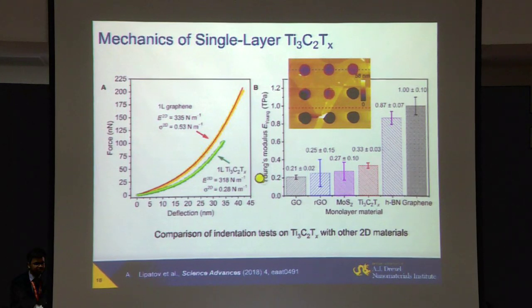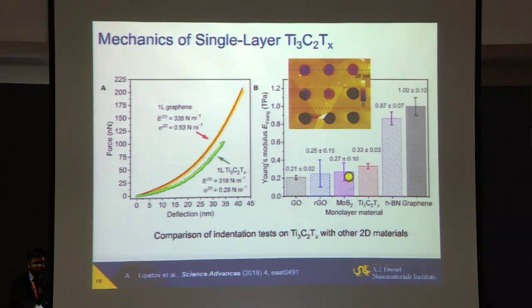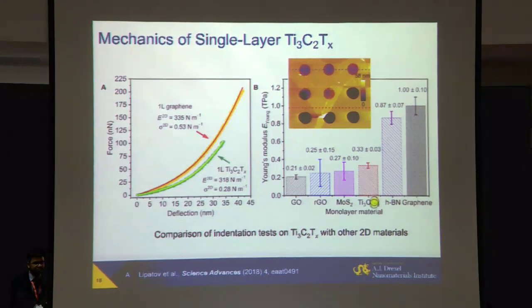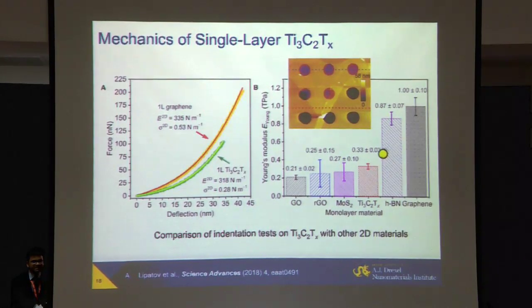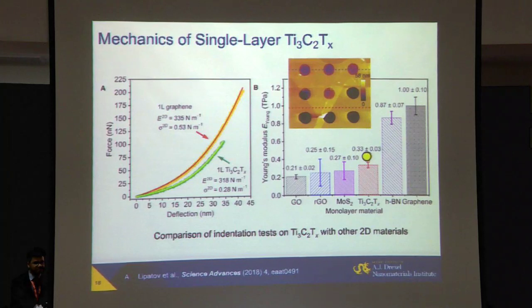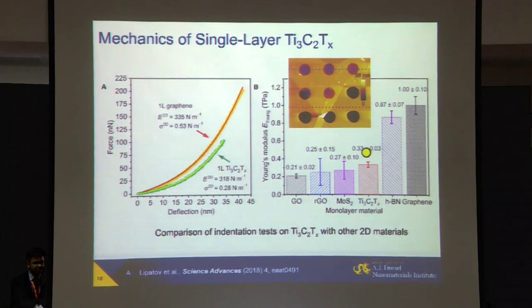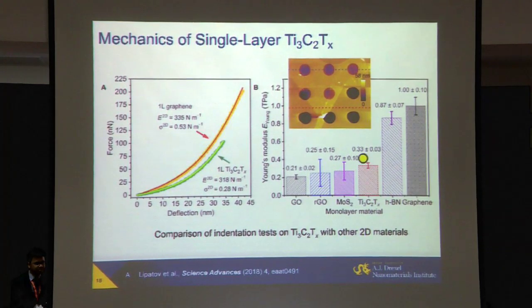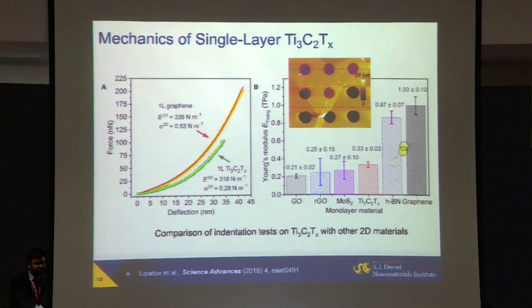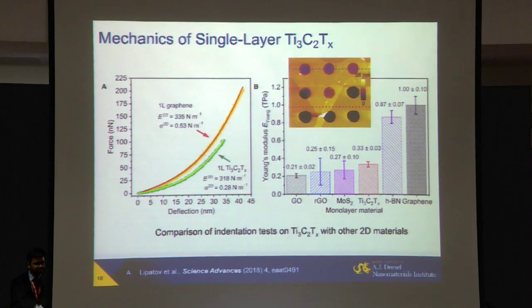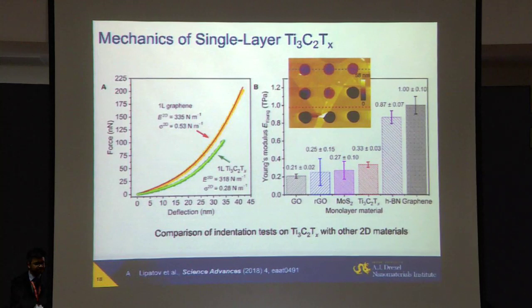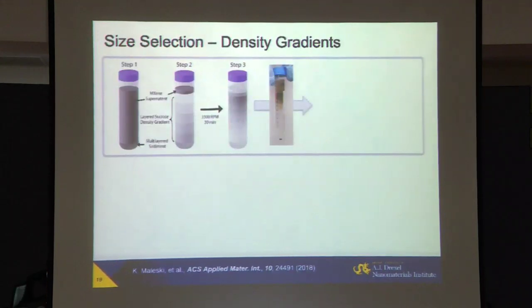If you take reduced graphene oxide, molybdenum disulfide, the very first MXene, titanium carbide Ti3C2, already had a high Young's modulus. We tested niobium carbide Nb4C3 now, and it has about 430 gigapascal modulus and about 30 gigapascal strength. So those are very strong materials to add here.